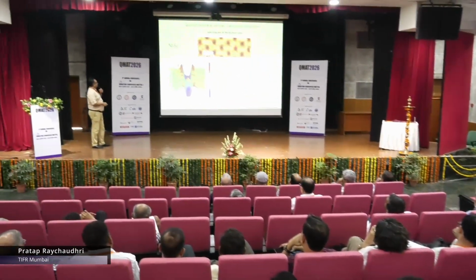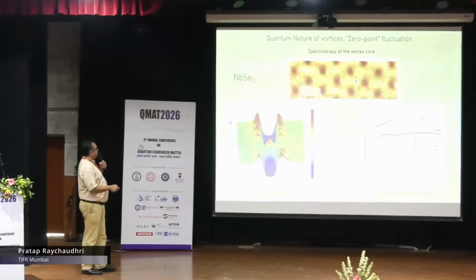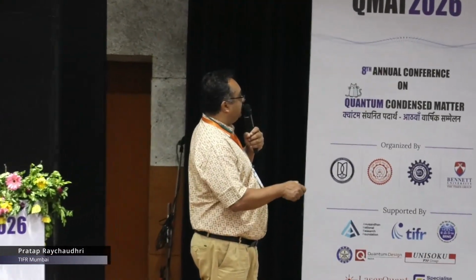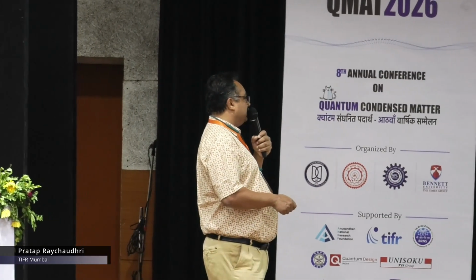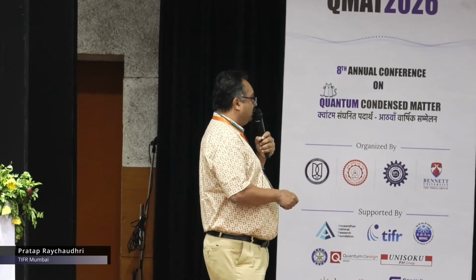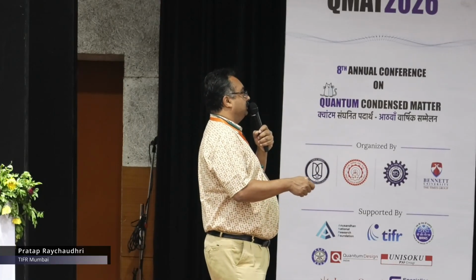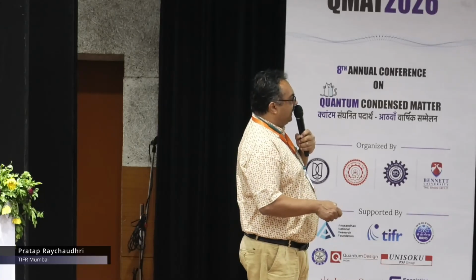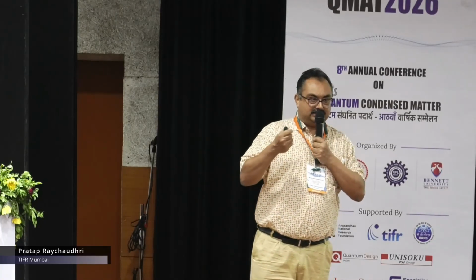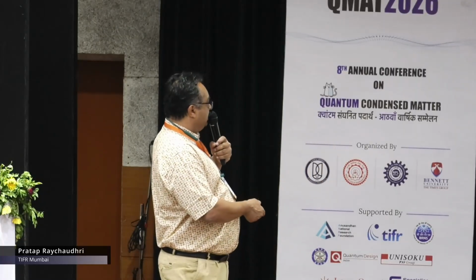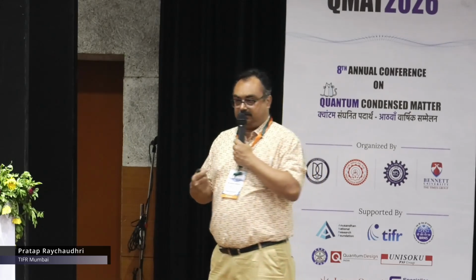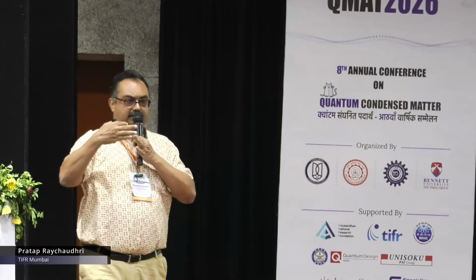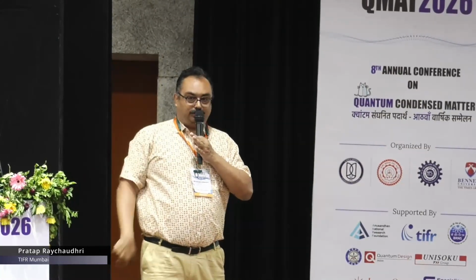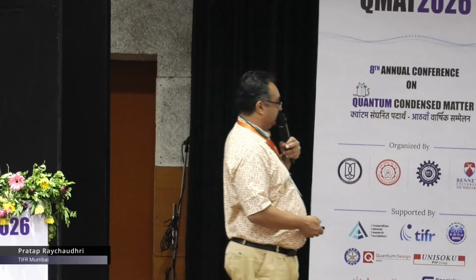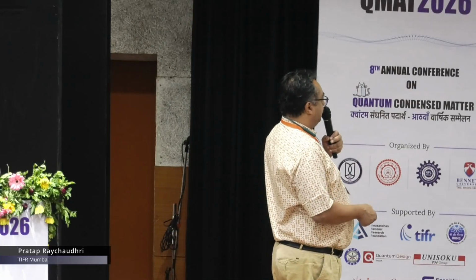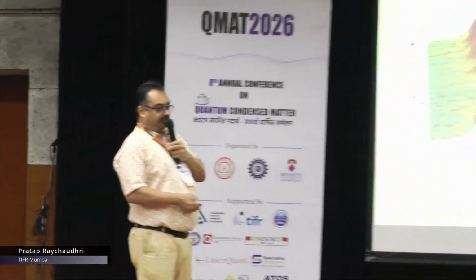Now, for this, we studied very carefully the vortex core spectroscopy. If I take the spectra along a line passing through a vortex in a very clean niobium diselenide crystal, I have earlier shown you that at the core your spectrum should be completely flat. It is flat, for example, here, when you take a slightly dirty sample. But if you have a very clean sample, you can also get this small peak, which is called the Caroli-de Gennes-Matricon peak. This is essentially because you are confining the normal electrons in 2 dimensions within this vortex core, which is of the order of 10 nanometers or so. So at the vortex core, you can get this kind of small peak, or it can be flat.